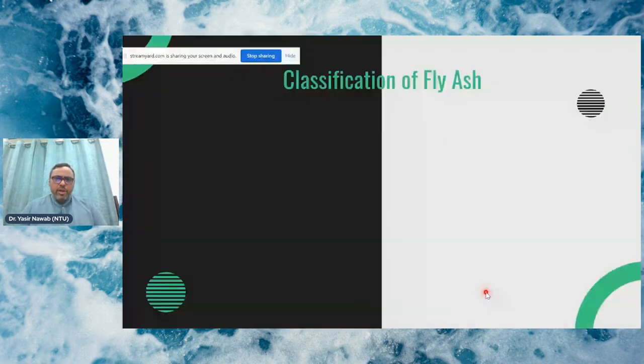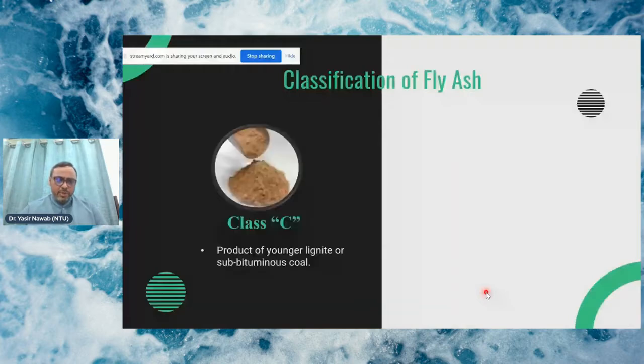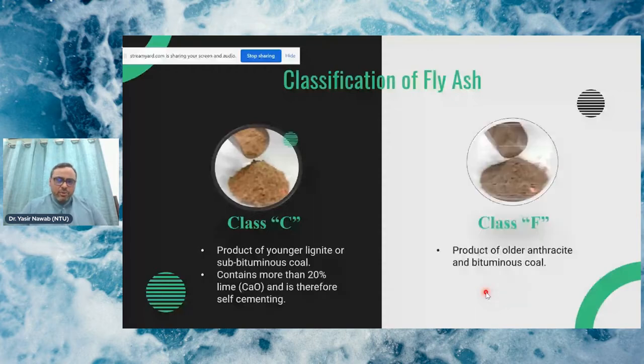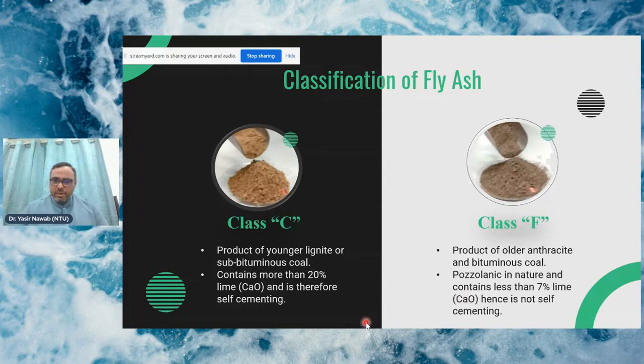So if we classify the fly ash, there are two types, two classes, class C and class F. So class C is that which contains more than 20% lime. So it can be used easily in the civil applications as it's self-cementing. And class F, mainly it contains less than 7% of lime. So it's not self-cementing, you have to add additives.